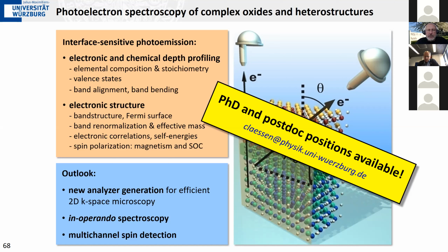I mean, I have this picture that we ought to have a trivalent titanium atom, and very often we do not see that. Very often we see only 4+. And then by systematically changing the different substrates, by putting in this diffusion barrier, the LAO between the STO and the LTO, by putting up a capping layer, by looking at the depth profile, by changing the photoemission escape angle, we get this conclusive picture that some of the excess oxygen comes from the substrate, and that has to be avoided by choosing a suitable substrate.